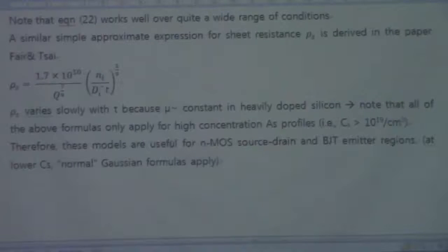And then we convert that concentration of arsenic to the sheet resistance, because that's just a one-to-one match, okay? The dopant concentration can be matched to the resistance in a semiconductor. So we just use this equation to get this y-axis as the sheet resistance, and this is the distance. And you can see a pretty close matching between the calculation and the experimental results.